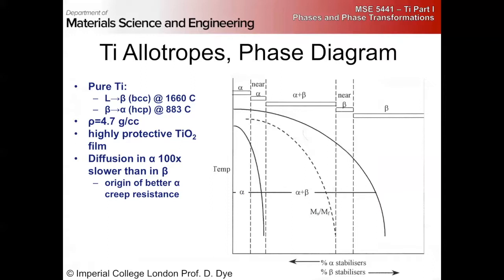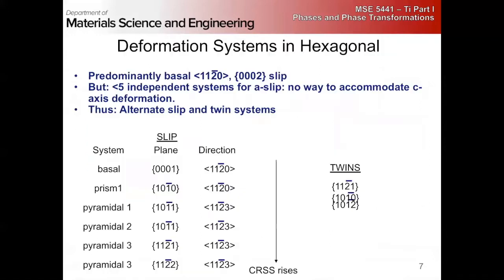Why is titanium of interest? It's high strength to weight for the most part. Corrosion, very highly resistant to corrosion. It is so far the only biocompatible metal. Well, austenitic stainless steel, certain grades of austenitic stainless steel. But if you have surgery and they leave something behind, like a pin or a screw or a new knee, it's titanium for the most part. And very slow diffusion, so if we can be in the hexagonal regime, we can have also very good creep resistance.